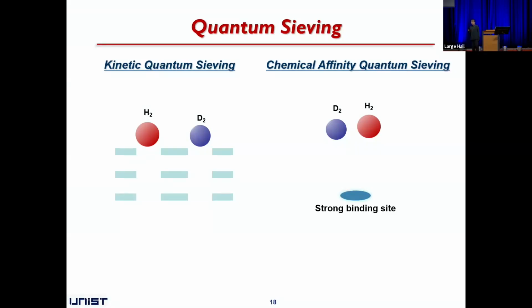It means that they can have different de Broglie wavelengths. So an appropriately small pore can act as a diffusion barrier toward the lighter hydrogen more than the heavier deuterium. From previous research, people suggested that to see the kinetic quantum sieving effect toward the hydrogen isotope mixture, we need to have a 3 to 3.4 angstrom pore size.